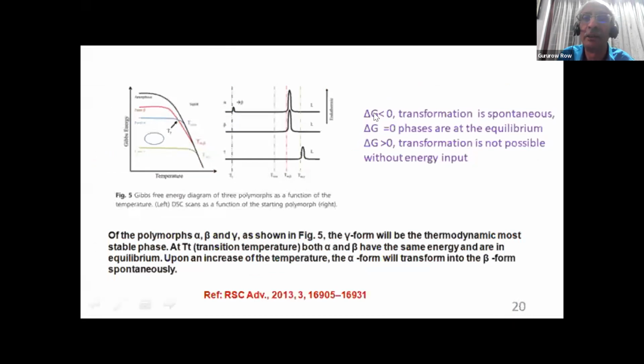When the value of delta G is less than 0, transformation is spontaneous. When delta G is equal to 0, the phases are in equilibrium. And when delta G is greater than 0, transformation is not possible. This is the thermodynamically stable form. But we can always change it with energy input. We can put in energy in different ways: we can change the pressure, we can change the temperature, and so on. As a consequence, even delta G greater than 0 can be overcome.